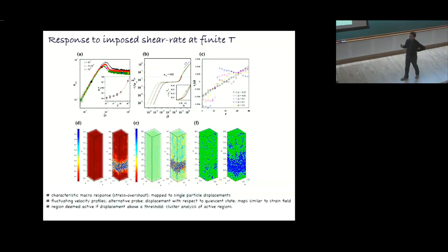Numerical simulation can observe the motion of single particles in the system. If you observe the motion of single particles in the system, you can compute the mean square displacement of each particle and take the average. The average mean square displacement as a function of strain, you see that initially there is some ballistic behavior when the particle is still within the neighborhood of the cage, then there is a plateau where it's still localized, and then the cage breaks, and eventually you have diffusion. We can identify at what time scale this is happening. Eventually, in all cases, you have diffusion, which is the steady state.